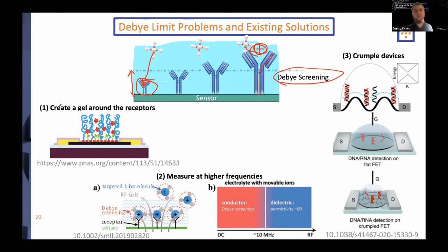One would be to create a small gel around these receptors to make the analytes go into the gel and react with the bioreceptors without undergoing this Debye limitation. Another very exciting approach, which I don't think has been fully explored yet, is to measure this device at higher frequencies, above 10 megahertz. This is when water, instead of being more like movable ions, becomes more of a dielectric. Then you can approach it as a normal silicon dioxide dielectric, so you do not have this Debye screening.